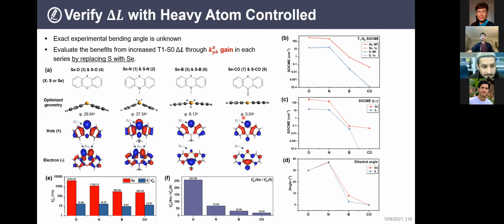And also when we gradually change the dihedral angle from higher to lower, from the computation, we are seeing gradually decreasing spin-orbit coupling value. And note that this is in the log scale, so it is actually decreasing a lot. Experimentally, we synthesized all these materials, both in their selenium derivative and the sulfur derivative. And we found that as we gradually move from oxygen to carbonyl, larger dihedral angle to smaller dihedral angle, it generally followed the trend that the k, which is the phosphorescence rate, is decreasing. The trend is not that pronounced in the sulfur derivative, but generally follows the prediction.